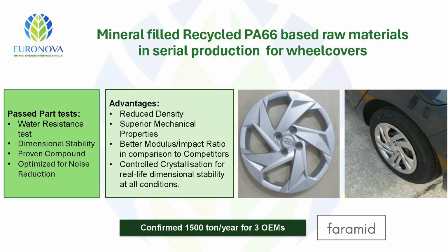And this was also validated, but does not include graphene yet. This is a natural 2D mineral acting like graphene, at just 15%, with recycled polyamide coming from cord tire. And this is validated by 3 OEMs. Now, this November, with our new extruders, we will start to produce this material, 1,500 tons per year for 3 OEMs, and then we will extend the technology.